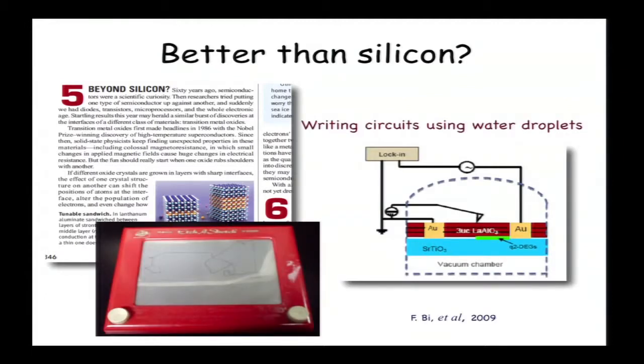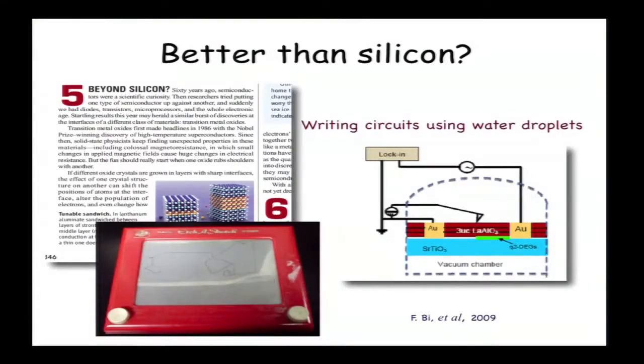And one interesting application is to use the fact that when we have three layers of lanthanum aluminate, the system is insulating, but it's on the verge of being conducting. And in order to make it conducting, we need to slightly polarize the system. And that can be done using water. So what they were doing, they were using water, writing their circuit. Wherever there is water, it becomes conducting. But since they can also remove the water drops from the system, they have a chance to erase the circuit and then just rewrite a new one. So you can think about it as an Etch A Sketch for electronic circuits.